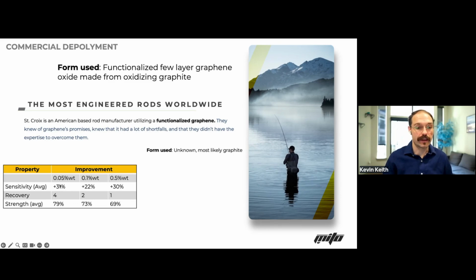So you'll see here that between 0.05 and 0.1%, you still get an increase at 0.1%, but nowhere near as 0.05. And then by the time you load 10 times more material at the 0.5, you're back up at that extremely low loading level. But because of the morphologies and the characteristics of this functionalized few layer graphene oxide, made from exfoliated oxidized graphite, we knew that there was going to be damping properties the higher the loading value you got. And then we knew that the strength at the 0.05% was going to be much higher than that. So there's trade-offs that you can do here depending on what chemistries and morphologies you want to put into the system, depending on what your goal is.